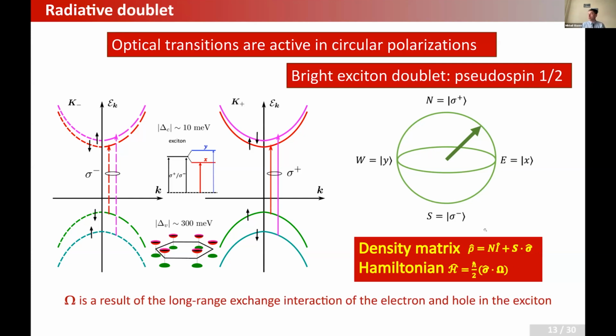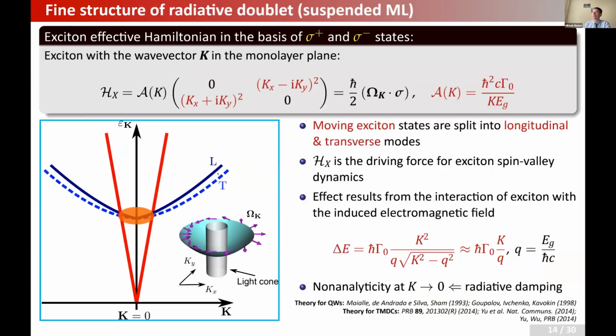So for excitons, in principle, you can also introduce the 2x2 spin, or valley in our case, density matrix. You can introduce the Hamiltonian, and this Hamiltonian has a kind of Zeeman term. And this omega depends on the exciton momentum, on the exciton wave vector, and is actually a result of the long-range exchange interaction which I have explained to you. And if the exciton now propagates, this omega is non-zero, and as a result, the excitonic states will be split. In fact, they will be split into two linearly polarized states, one along the exciton momentum, and another one perpendicular to the exciton momentum.